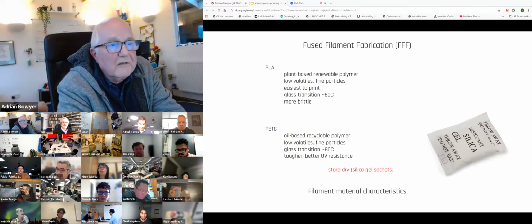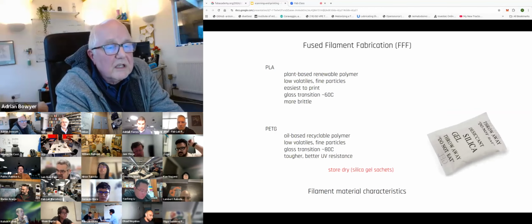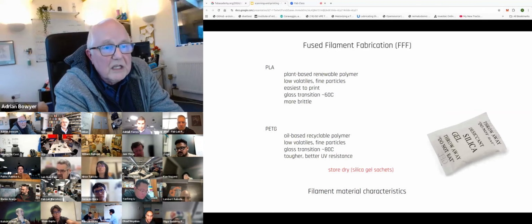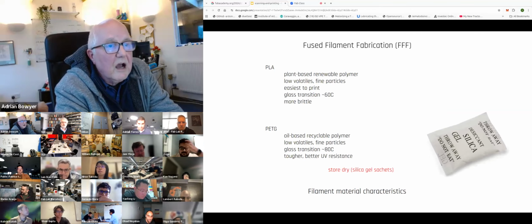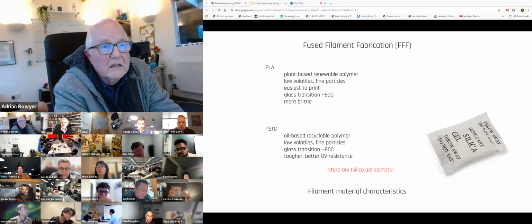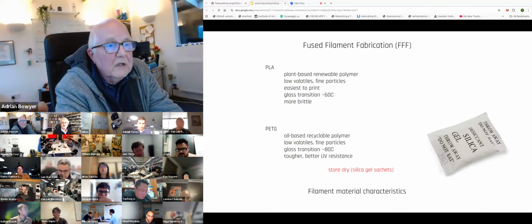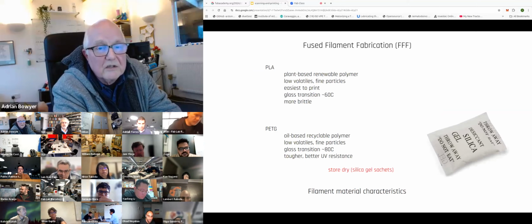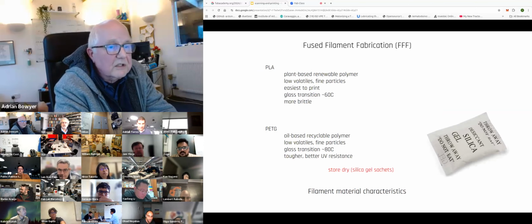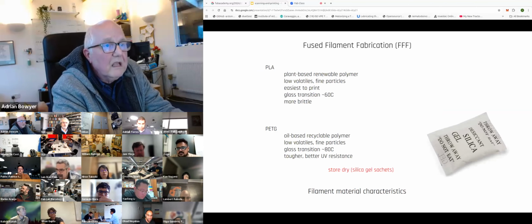And once we got our filament from our supplier, we had to take care of it. PLA in particular is hygroscopic, which is to say it absorbs water from the atmosphere. We want to put it in a container and keep the air in that container dry to keep it in good condition. So you want some sort of hermetically sealed container into which you put some of these silica gel pouches that keep the air in there dry.